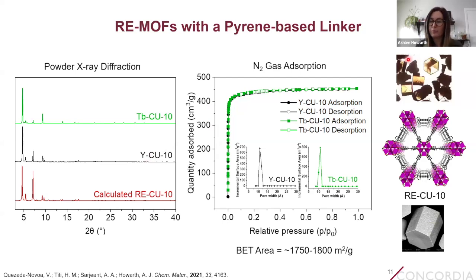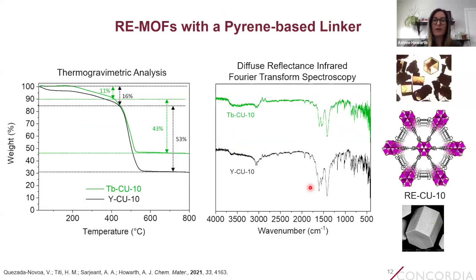This MOF also has permanent porosity, so we can activate the materials and get these nice type 1 nitrogen gas adsorption isotherms, showing that the MOF has BET areas of around 1,800 meters squared per gram and pores of around 10 angstroms in size. We can see that this MOF is also quite thermally stable. So using thermogravimetric analysis, the MOF decomposes at temperatures greater than 400 degrees Celsius.